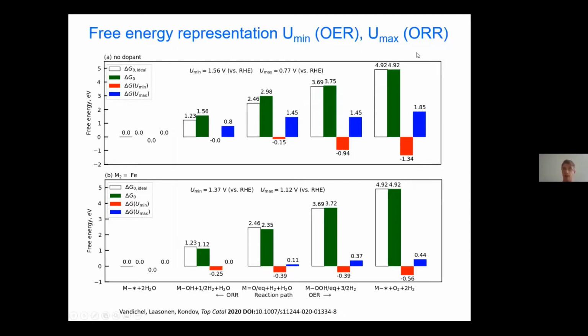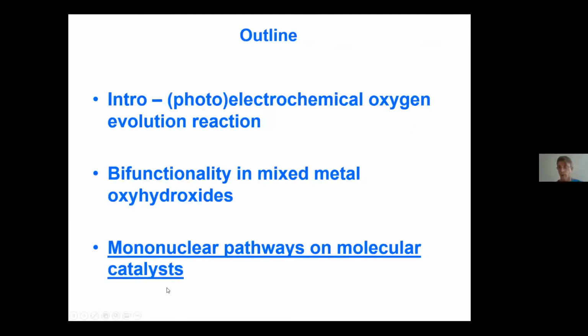The same, we can read this plot also for ORR, but then we have to read from right to left. So in the ORR process for nickel iron OOH with iron in the M2 position, we see that the last step, the generation of the empty site, is then rate determining. So that is it for metal oxyhydroxides.